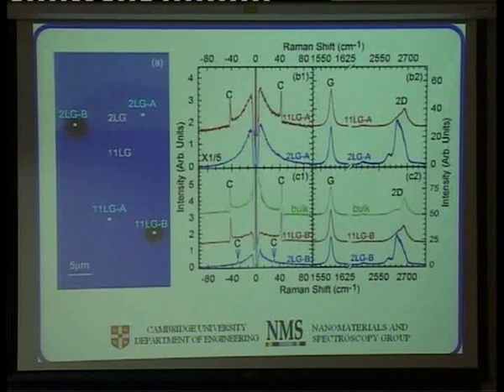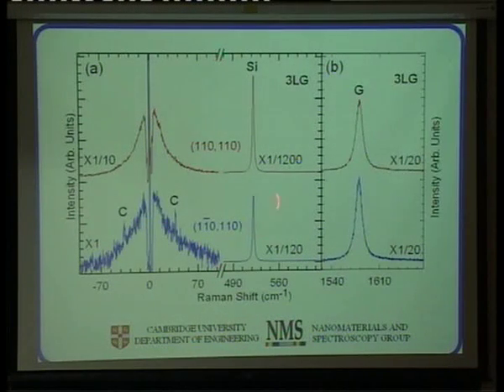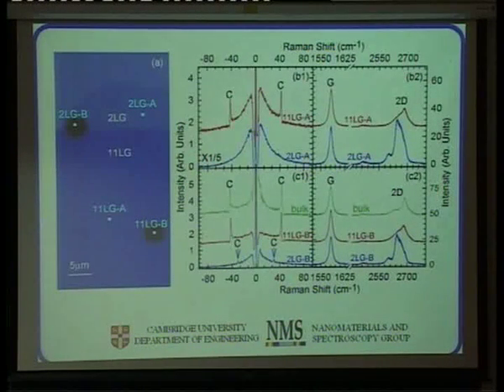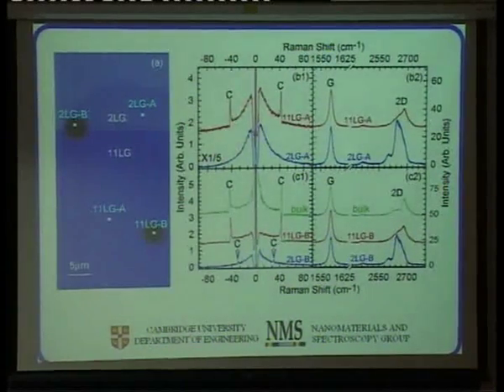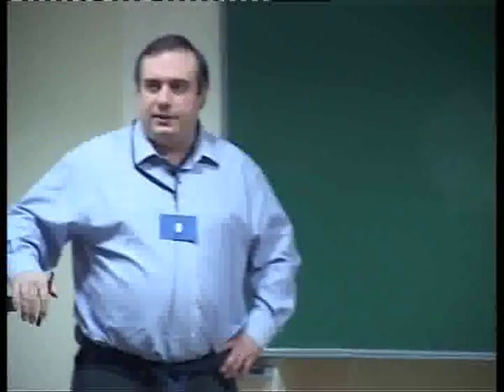Sorry, how many layers are there? This one is 3 layers, but it could be bulk, whatever. I mean, this 3LG means 3 layers of graphene. If it was 1 layer, you would not be able to see it. Silicon is the substrate, because usually you put graphene on silicon because you can see it with your own eyes because of the silicon oxide interference.